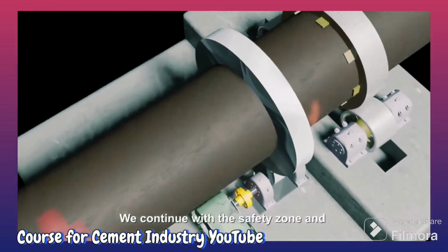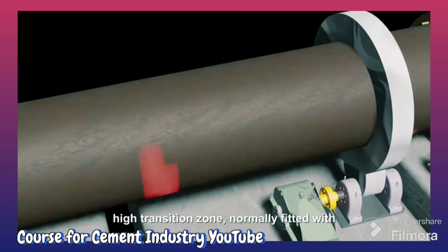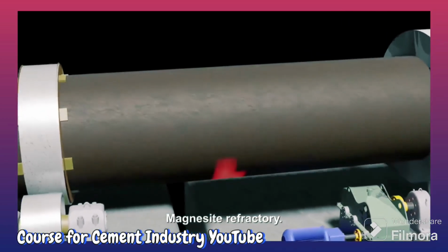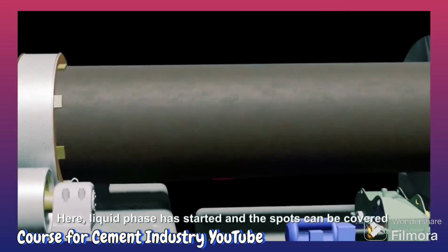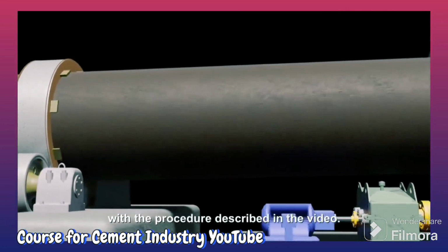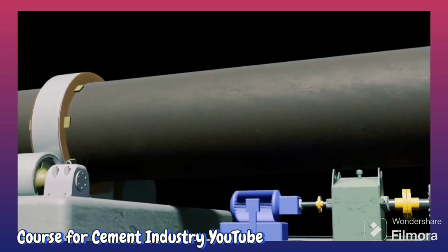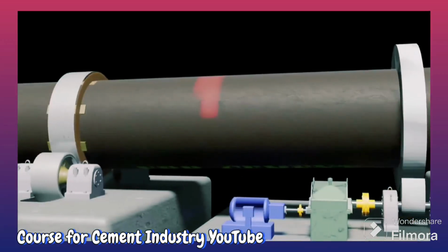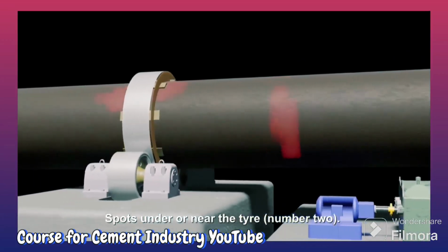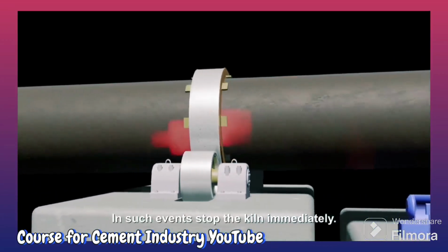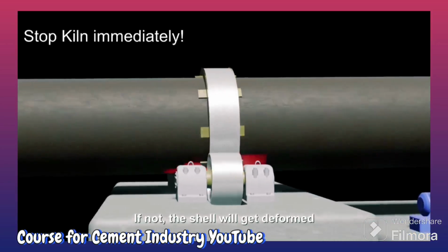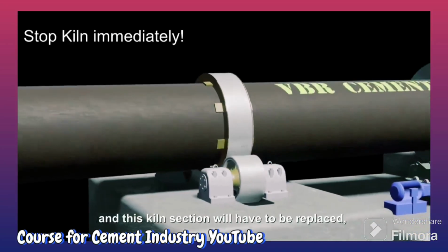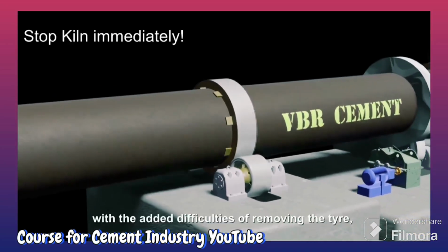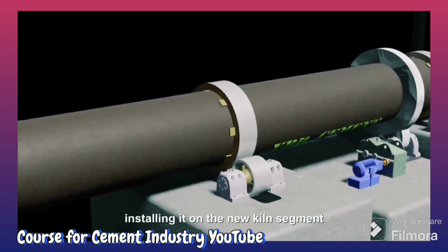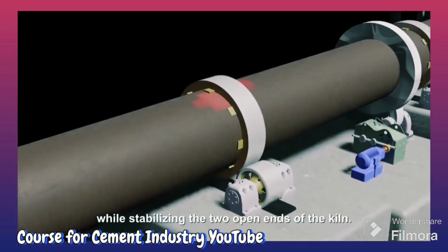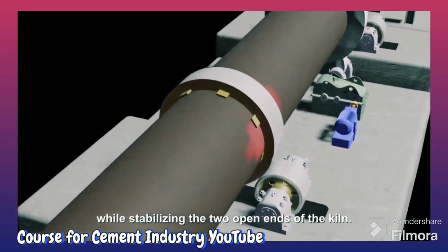We continue with the safety zone and high transition zone, normally fitted with magnesite refractory. Here liquid phase has started and the spots can be covered with the procedure described in the video. Spots under or near the tire: in such events, stop the kiln immediately. If not, the shell will get deformed and this kiln section will have to be replaced, with the added difficulties of removing the tire, installing it on the new kiln segment, while stabilizing the two open ends of the kiln.